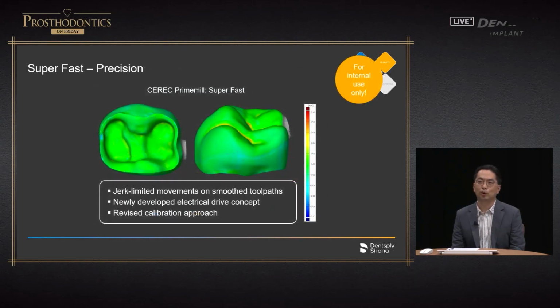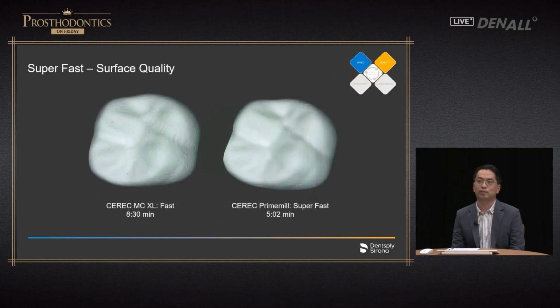And precision has improved drastically. What is interesting is that if time is reduced, precision usually also goes down, but here precision has gone up. In the case of the MCXL milling machine, you can see grooves not being formed appropriately when milled for 8 minutes 30 seconds, but in Primemill, even though it has been milled for 5 minutes, the groove has become much clearer.